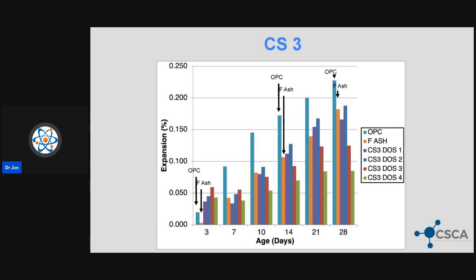And that's where a lot of people come up with the same indication. I think it is Sri Harsha who said that, hey, and I'm not looking at the comments, I apologize, we used this at 0.3% and I didn't see good results. Okay, you might have been using too much. You might not have been using enough. You might have been using a cement that doesn't work well with nano silica or colloidal silica, and it could agglomerate as soon as you distributed it into the mix.